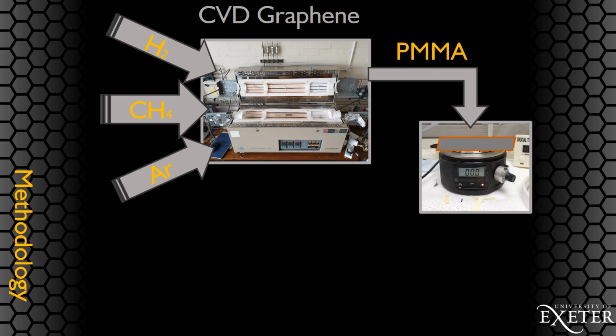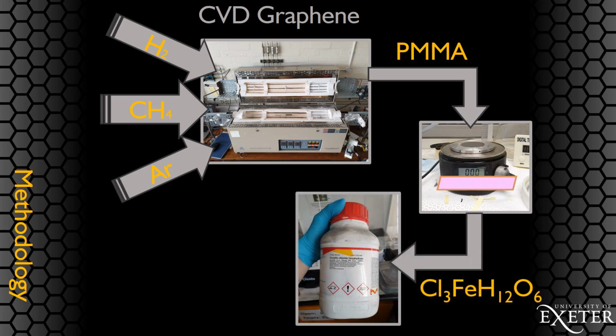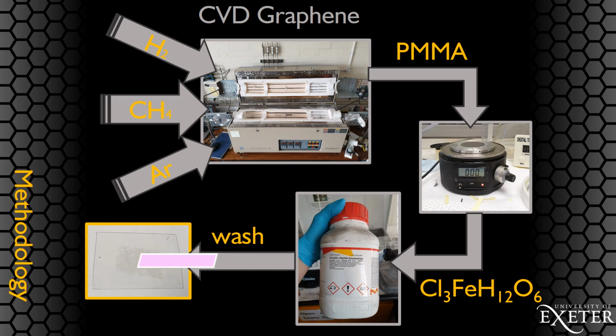One side of the sheet is protected from oxidizing the graphene by spin coating PMMA on top. To isolate the graphene layer, the copper is dissolved away using a solution of iron chloride, and once the graphene is cleaned with water, it can be dipped onto the substrate for further use.